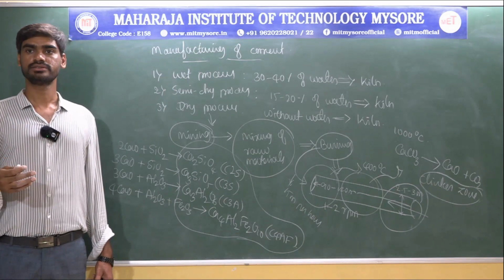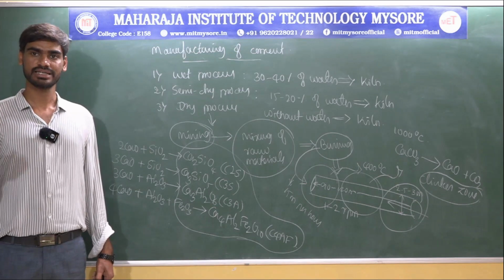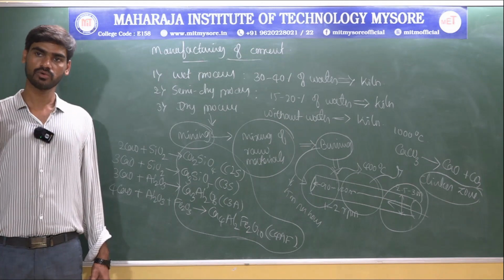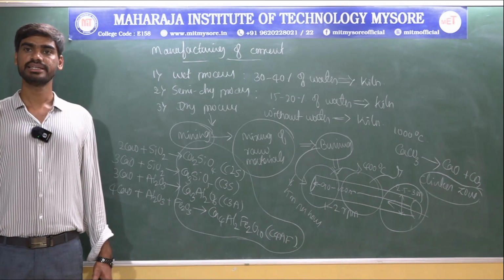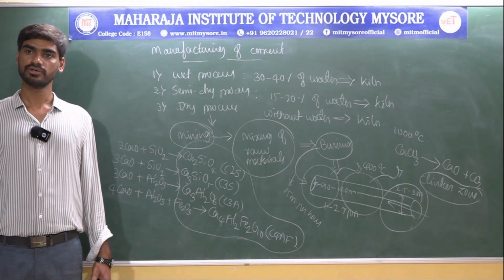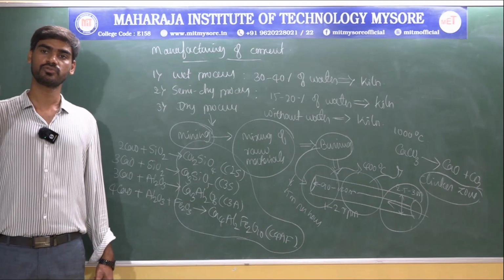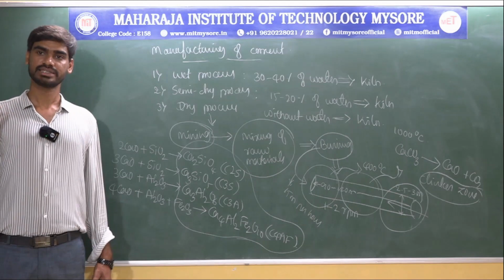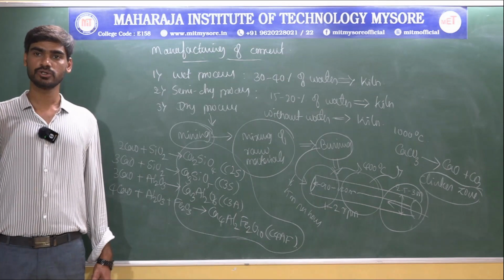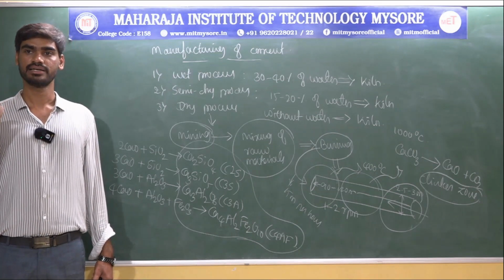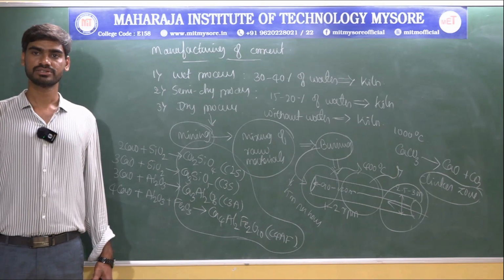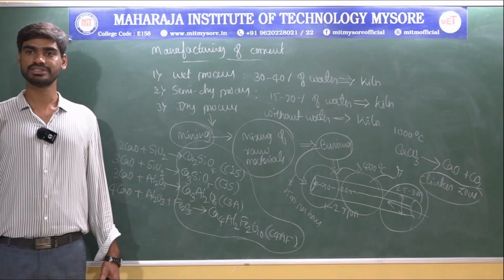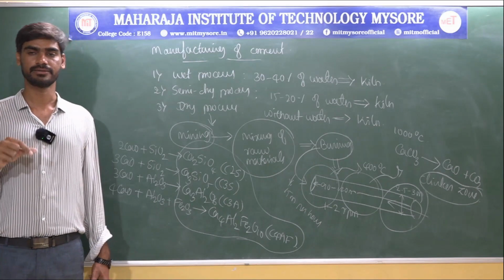Then the clinkers are ground finely into powder in a ball mill or tube mill, and during final grinding it is mixed with about 4 to 5% powdered gypsum, which acts as a retarding agent. Gypsum prevents the dissolution of tricalcium aluminate by generating tricalcium sulfoaluminate, which is insoluble and prevents too early subsequent reaction of setting and hardening.